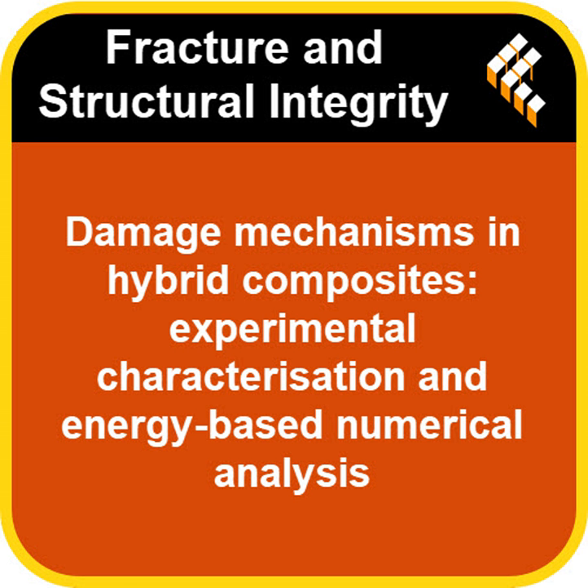So by looking at how much energy was being absorbed in each layer in the simulations, were they able to pinpoint where the damage was most concentrated? Like which specific layers took the most punishment? Definitely. Their detailed analysis of the intralaminar damage energy layer by layer was really revealing. It showed that in the hybrid composites, the outermost carbon fiber layers were taking the biggest hit. The ones on the very top and bottom. Essentially, yes, but it depended on the glass placement.